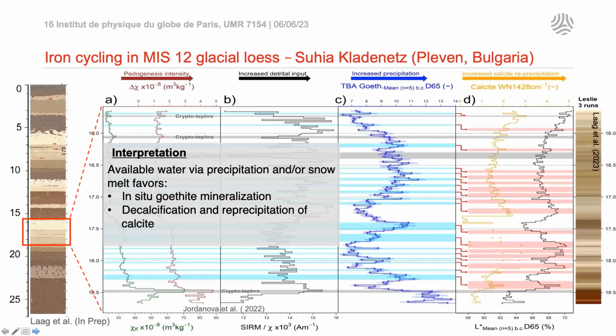So if we come back, we can interpret that the variations we're seeing in goethite content, in combination with the calcite content, indicate that available water, precipitation and or snow melt favors in situ goethite mineralization, and also the decalcification and reprecipitation of calcite in the horizon directly below. I know I'm over time. I have 2 slides left.